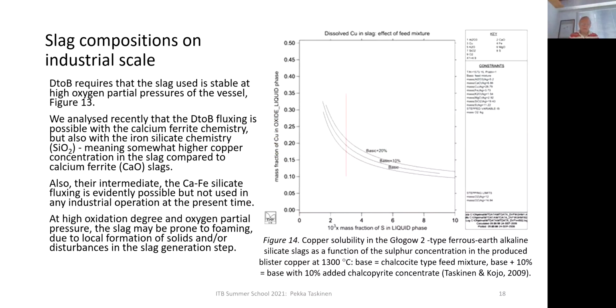So in these iron silicate chemistry cases, we have somewhat higher copper concentration in the slag, but it has appeared that this cleaning step in electric furnaces is rather robust and flexible and fast, and it doesn't very much limit the productivity. So this is an example from that Polish smelter, which is using modified iron silicate slags, and their operational point is at 0.3 weight percent sulfur in the blister,